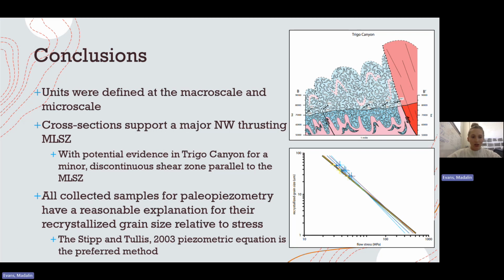And finally, going into the conclusions, all the units were defined at the macroscale and the microscale. Cross-sections support a major northwest thrusting Monte Largo shear zone with potential evidence in Trigo Canyon for a minor discontinuous shear zone parallel to the Monte Largo shear zone. And all the samples collected for paleopiezometry have a reasonable explanation for their recrystallized grain size relative to stress, where the Stipp and Tullis 2003 piezometric equation is the preferred method.